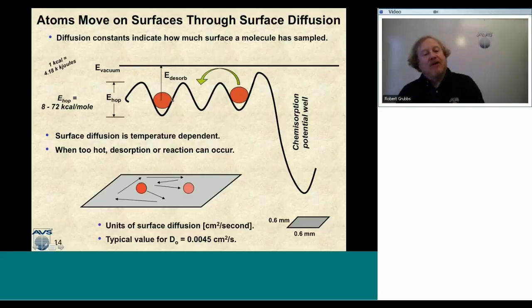So the hopping energy can vary quite a bit depending on the surface. And it can be like 8 to 72 kcals per mole, which can be pretty big. But we can see that happen when we do atomic layer deposition, as molecules will actually diffuse on the surface before they actually react. So this surface diffusion, you can see, is temperature dependent. As I increase the temperature, I increase the energy of the molecules on the surface, and they can bounce around more quickly on the surface.